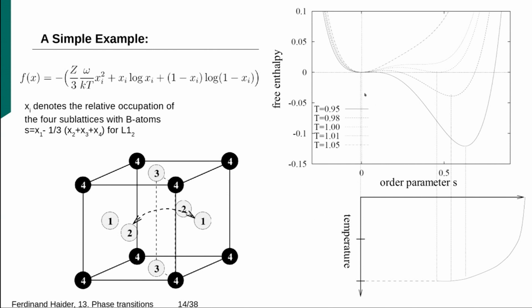So at high temperature, the minimum is here, the order parameter is 0. And at very low temperature, the order parameter is 1. You have this slow decrease in order, so you can always put this equilibrium degree of order here to this curve here. And here you find this abrupt jump from finite order, 1/2 or so, to 0.